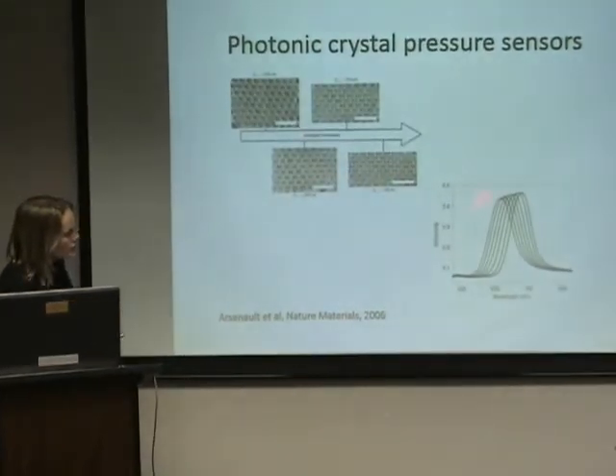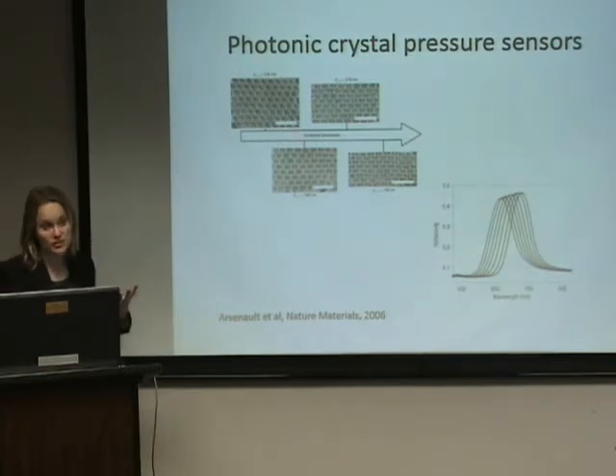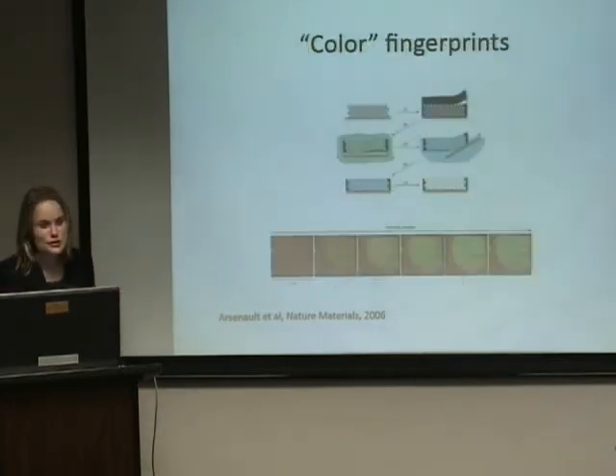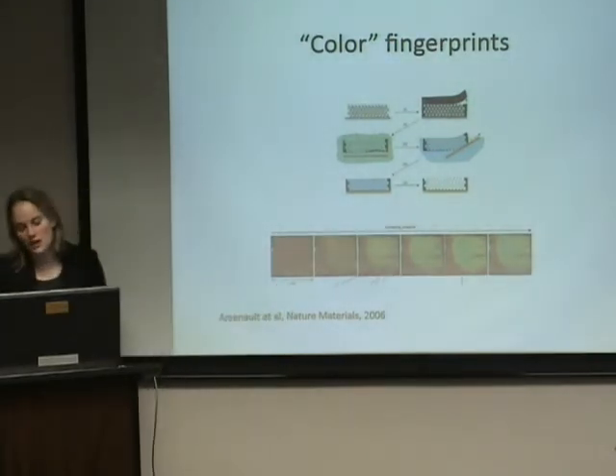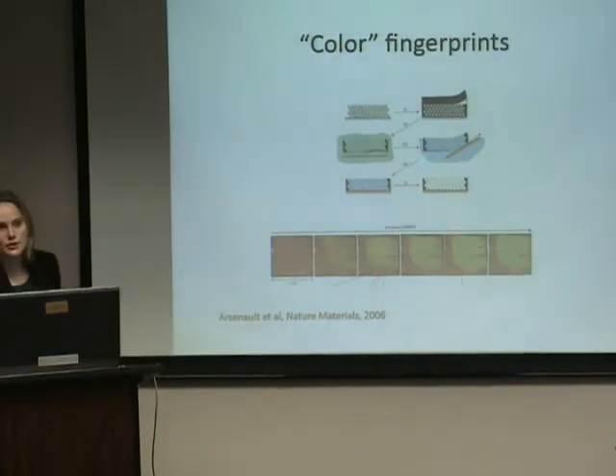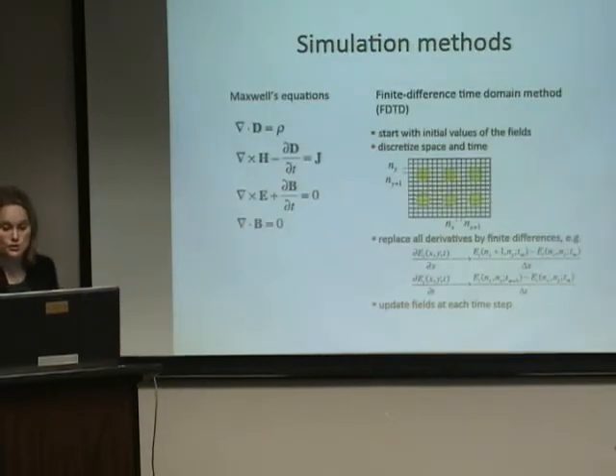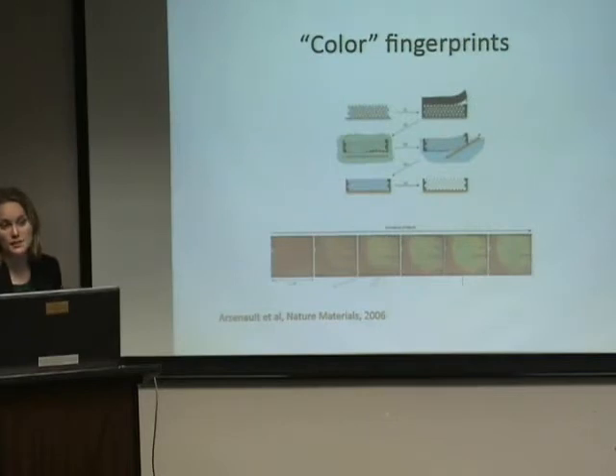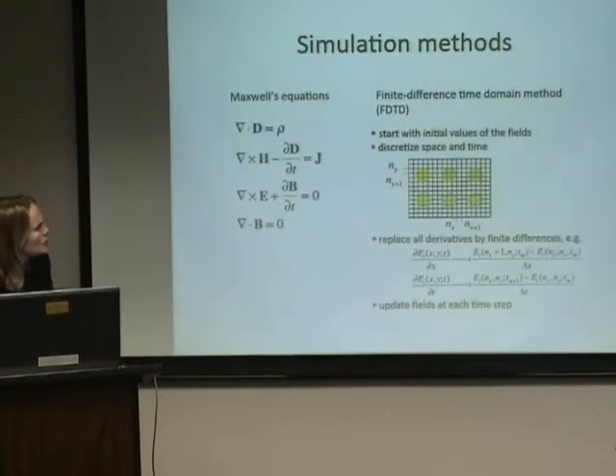As you apply pressure, you shift the band gap. A shifting band gap visually looks like a change in color. It changes the wavelength for which the reflectance is optimum, and so it shows up as a change in color. So in this paper, they were calling this color fingerprints. So here then is one example of how you can think about pressure sensing based on these optical techniques. Other experiments have been done where people have used different structures. This is one example. You can use a photonic crystal. You can also use some sort of resonant element, and then as you stretch it, its resonance changes, and you can do sensing. And this has been applied in a number of different contexts, though not so much with strain.